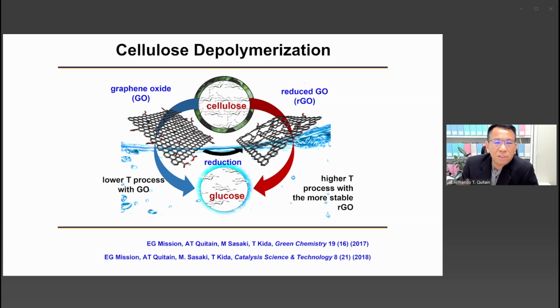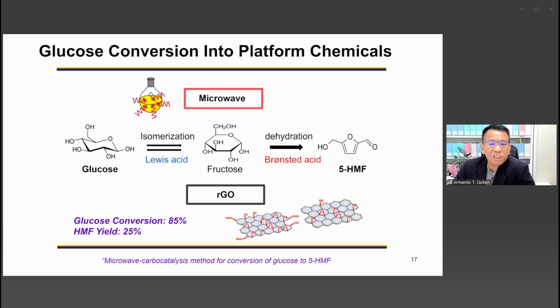Now, after getting glucose, we can convert this into more useful chemicals. And that is by isomerization process. Here, we need Lewis acid in order to get fructose and Bronsted acid for dehydration to form 5-HMF. And we were also successful in getting glucose conversion of 85%, but the yield is relatively low at about 25% at the moment for 5-HMF.